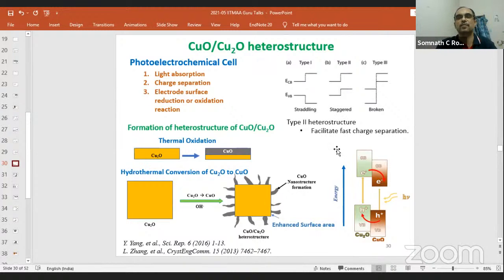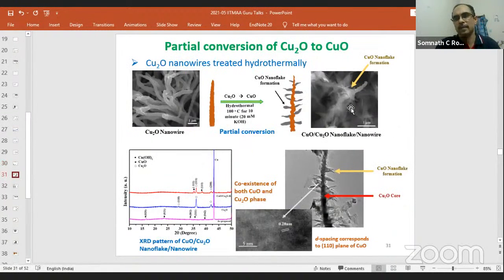Type 2 heterostructure is, as you can see here, where the conduction band and valence band of one material are higher than the respective conduction and valence band of the other material. So what happens? The electrons go this way and the holes go this way. But we found that this had been attempted in layer form, thin film form. We thought, no, we are the nano guys. We have to do it in a different way. We are the real estate guys, vertical guys. So we had to do it in a different way. We revisited the old problem with a completely new perspective. So here we first made Cu2O nano.